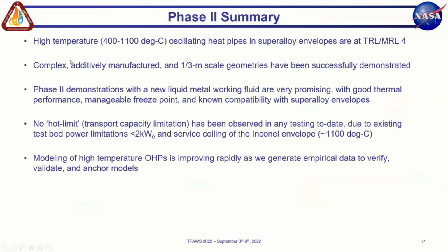So in summary, high temperature, we call that perhaps 400 to 1100 degrees C, oscillating heat pipes in superalloy envelopes have risen to TRL, MRL 4 through this effort. We've made complex, additively manufactured geometries up to third meter scale successfully, so high yield in the manufacturing and successful OHP function. The phase 2 demonstrations with the new liquid metal working fluid are very promising. We have good thermal performance, a manageable freeze point, and what's really important to us, because it was not the case in phase 1, is that we have a heritage of these liquid metal working fluids with superalloy envelopes. So the compatibility and corrosion risk is low, and we're pleased with that.